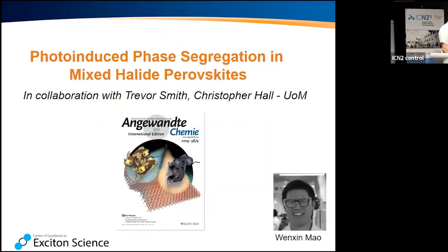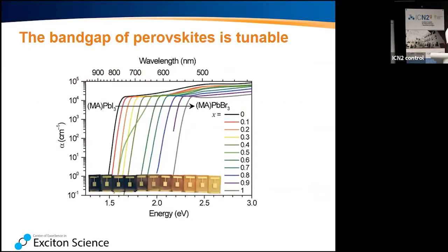We also use those crystals to look at photo-induced phase segregation. One of the amazing properties of perovskite is that you can tune the band gap, and the most effective way of tuning the band gap is by changing the halide ratio. So if you have a pure iodide perovskite, it has a band gap in the range of about 1.5. If you have a pure bromide one, it has a band gap in the range of about 2.2. And any mixtures of bromide and iodide in between give you band gaps that sit between those two extremes. It's fantastic if you think about it.